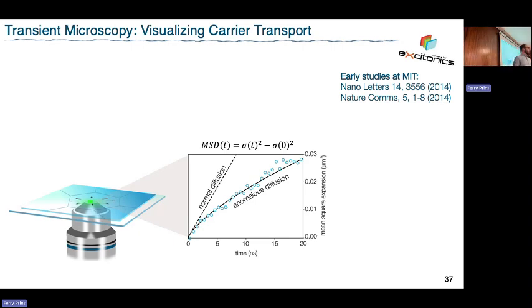And this is our first indication of disorder. You excite everything equally, but now your energy landscape has all these valleys, and your carriers tend to go down in these valleys, and they get trapped. And when they get trapped in the valleys, they cannot move as fast as when they are on top of the mountain. We're going to get to that in a second.